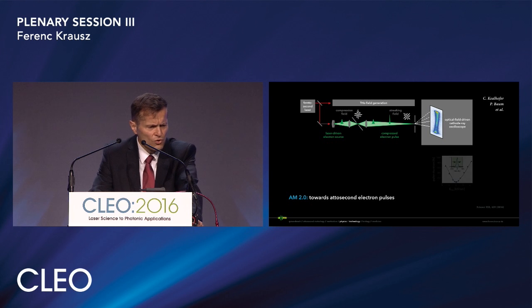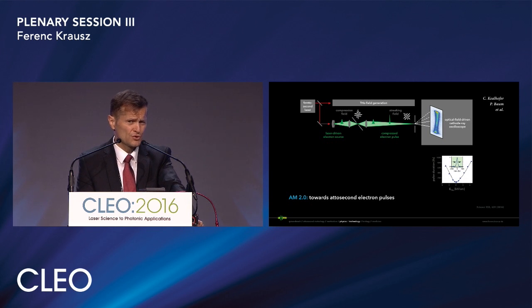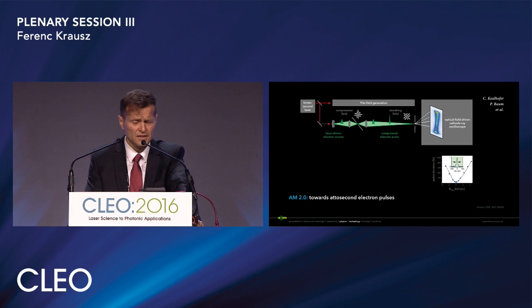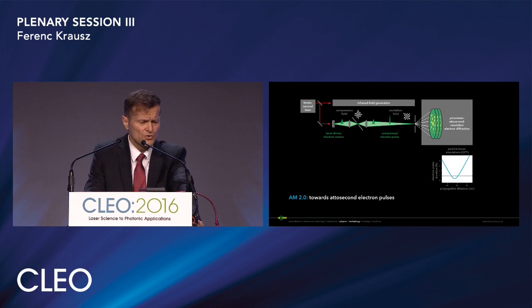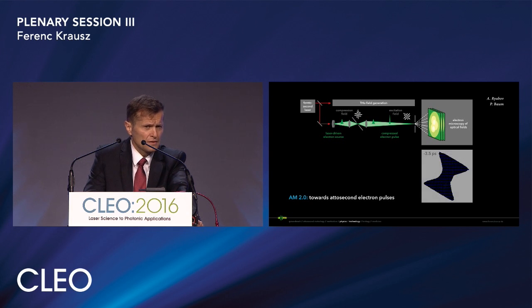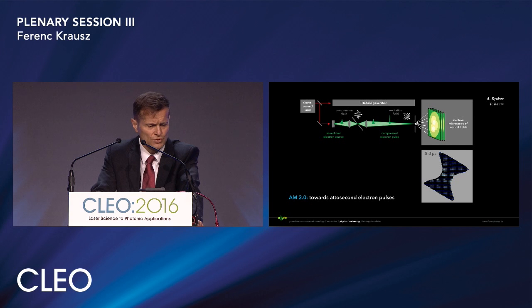C. Kealhofer, Peter Baum and co. recently demonstrated tenfold temporal compression of single electron pulses and their temporal characterization with the controlled field of single-cycle terahertz light. Scaling the technique to more rapidly varying fields in the infrared holds promise for picometer attosecond resolution electron diffraction, hopefully in the foreseeable future. As a first application, the optical field controlled single electron wave packets have been used for imaging the spatial distribution of terahertz fields in a bow tie antenna, as you see here.